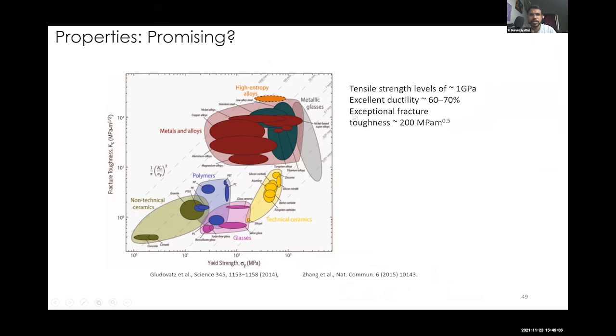Okay. So this is one paper which puts high entropy alloys here in the graph. Fracture toughness is in y-axis, yield strength is in x-axis. Very high fracture toughness is found for certain high entropy alloys. It's basically cobalt, chromium, iron, manganese, nickel, that high entropy alloy. And people have figured out that has extremely high fracture toughness. Tensile strength levels of above 1 gigapascal, 60 to 70% ductility, which is extremely high. Exceptional fracture toughness, 200 MPa meter power half.